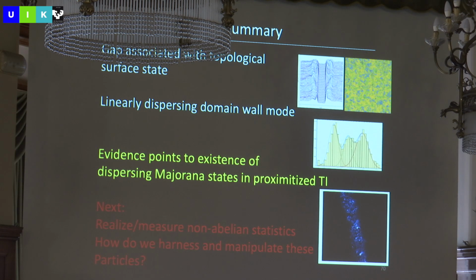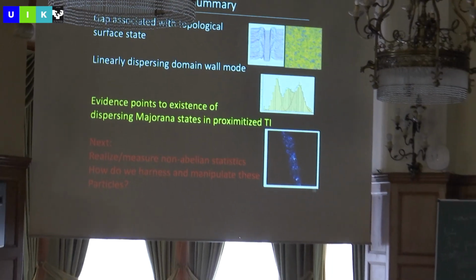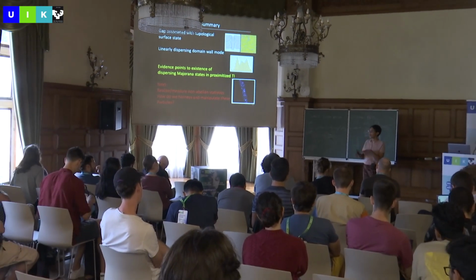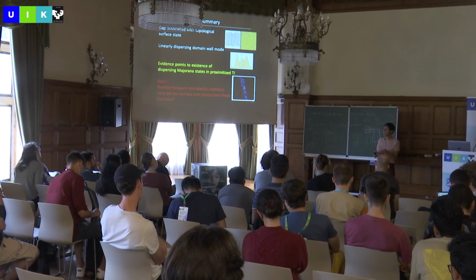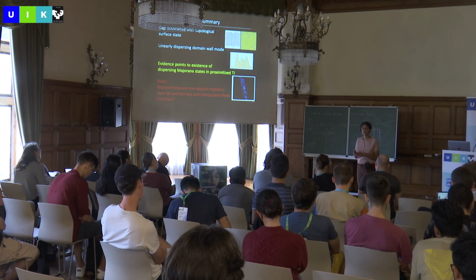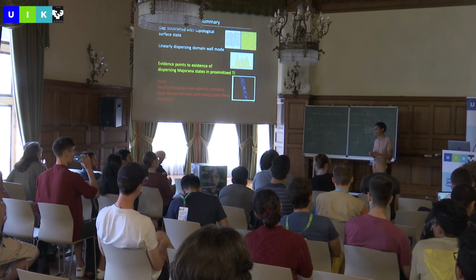And then if you are able to find this kind of a domain wall where the crystal has a phase shift in real space, so the two sides of the crystal are shifted in real space, that results in a pi phase shift in the superconducting order parameter. So at that boundary, you see states filling up the superconducting gap in this very uniform fashion. Okay, I'll stop here and take your questions.